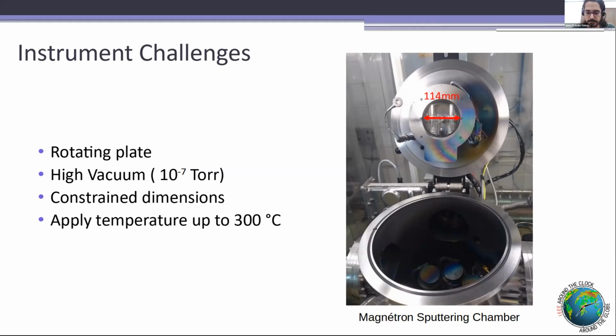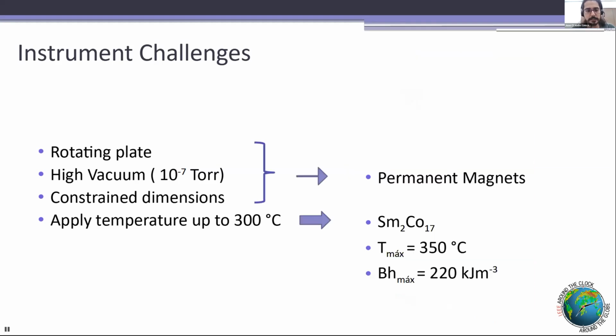So the solution that we thought about is to use permanent magnets that are totally compatible with high vacuum, and they are great to produce high magnetic fields in constrained dimensions, and it's easy to produce small permanent magnets. For a rotating plate, it's perfect because you don't have wires to entangle everything. And applying temperature up to 300 Celsius makes the system versatile for the deposition of several alloys that have phase transitions or structural transitions with temperature.